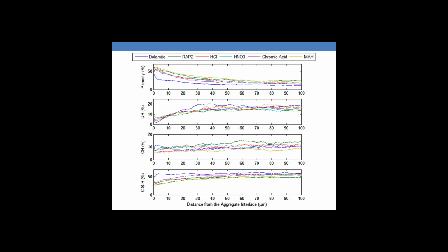In the end, no. So basically we treat the asphalt, it's improving our work of adhesion, our interfacial energy between cement paste and asphalt, but it's not affecting our ITZ. So the ITZ is still pretty much just as porous, with just as little CSH, things like that. So there are minimal benefits, it seems so far, for these treatments.